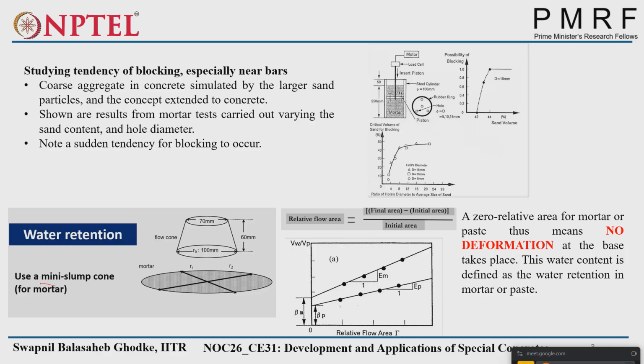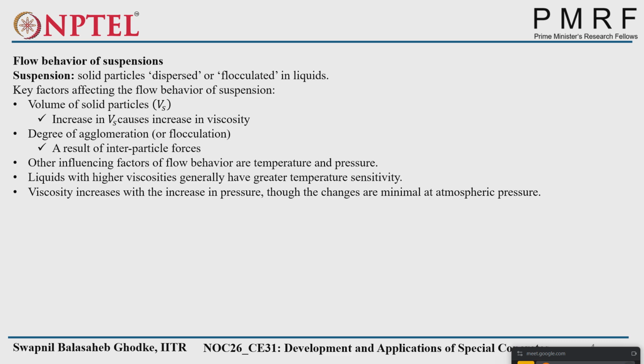One is understanding the amount of sand content and coarse aggregate content, and another is how to identify the water retention of the mortar mix. So basically, the flow behavior of any cementitious system is that of a suspension. Suspension means solid particles either dispersed or flocculated. Dispersed in the sense that there is a certain distance between the particles, and flocculated in the sense that they are closely together. So if you want to see the volume of solid particles, it is Vs.